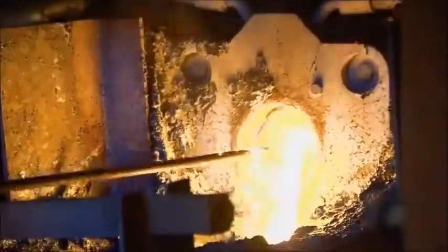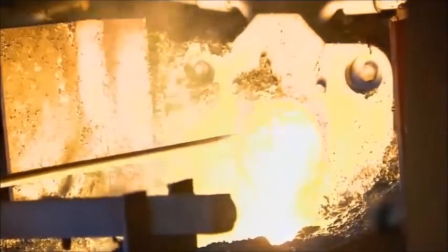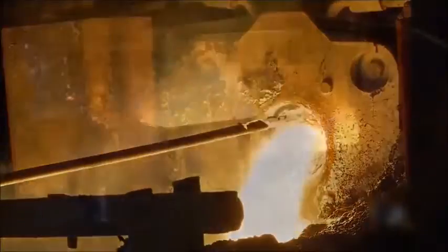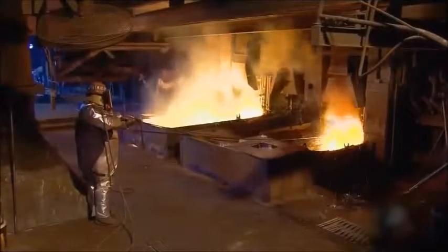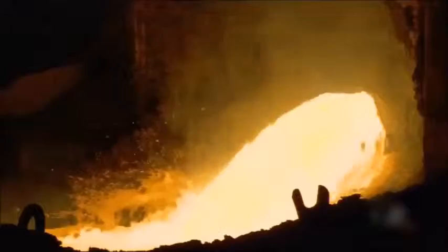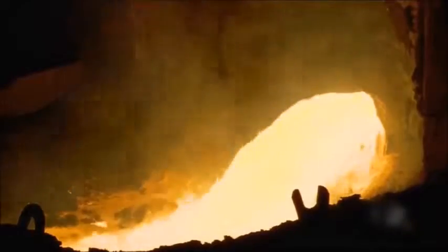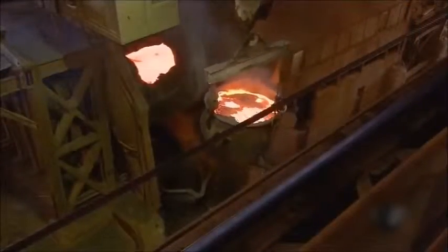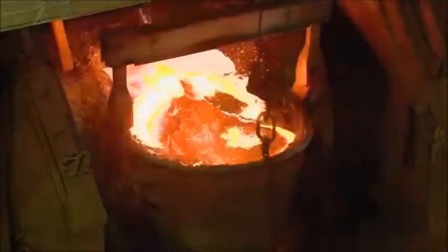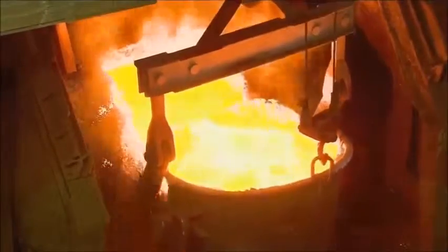In the intense heat of the furnace, the silica sand melts to form a slag that absorbs the iron and other unwanted minerals. The slag floats up and the copper sinks. Its purity is now 60%. Then it's into a second furnace, where they up the copper content to 98%.